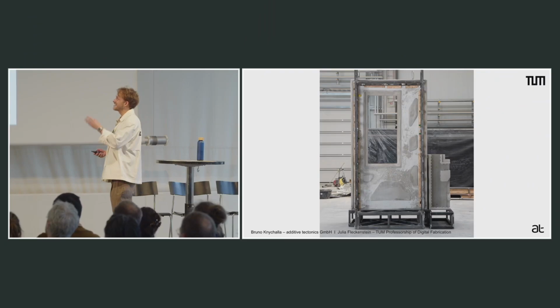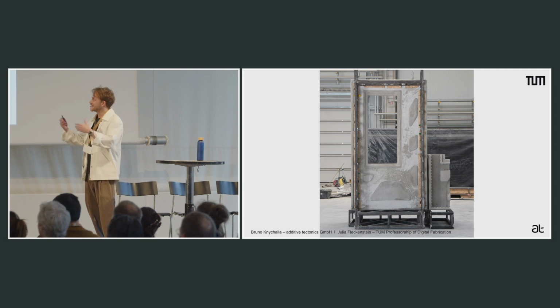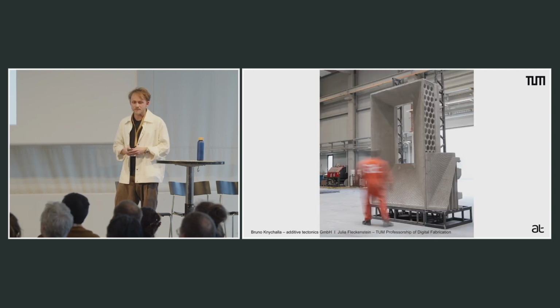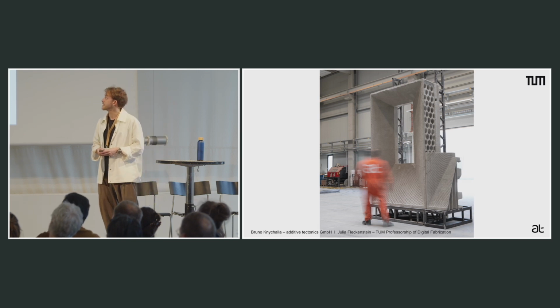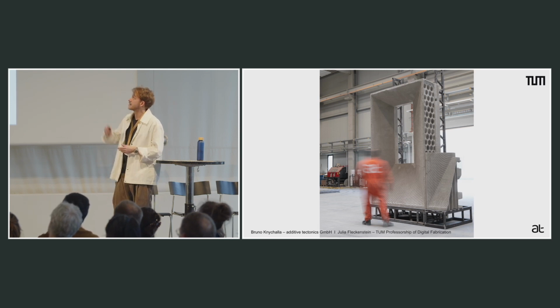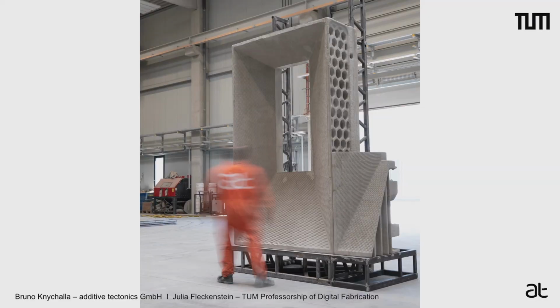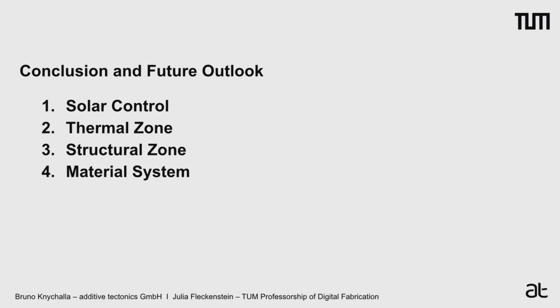Yeah, but it didn't crack so much. And here you can see the inside of the part. Basically, this you would see from the inside of the building. And here you can see the outside of the finished element. You can also see the thermal zone here. And we also fabricated a smaller part next to it to see the tolerances and to see how well the dry joints would work.